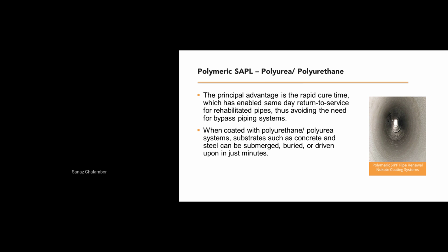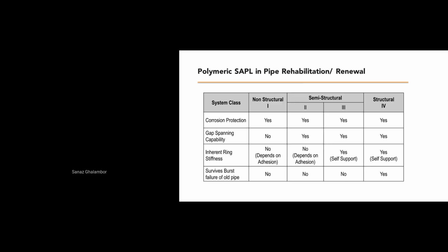So when the pipe is lined with polyurethane or polyurea SAPL, the substrate, which can be concrete or steel or whatever, can be submerged, buried, or driven on as soon as we get to the tack-free time. So very fast back to service is possible with this technology, which makes this technology very unique.